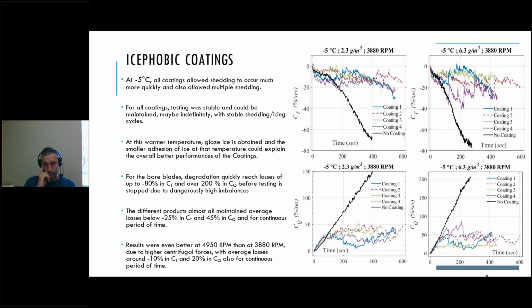So if we look at the plot, the black curve shows the results that I have presented before, when there's no coating present on the blade, so for the bare blades. So we see the fast and significant degradation of the performances as a function of time until there's a big shedding event, and then the vibration levels increase and become too high, and we have to stop the test for safety reasons. With the 4 icephobic coatings that we tested, a different scenario occurs.